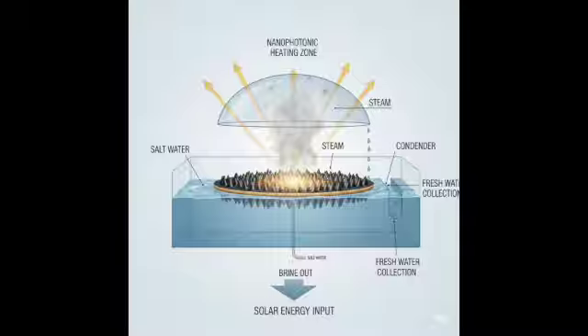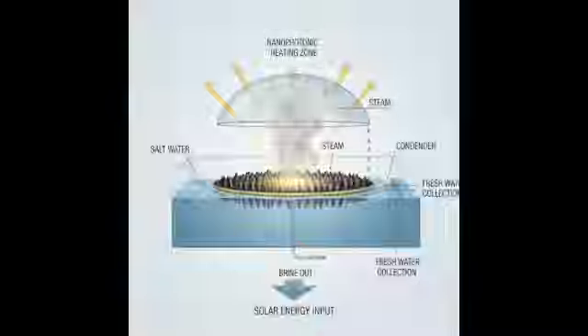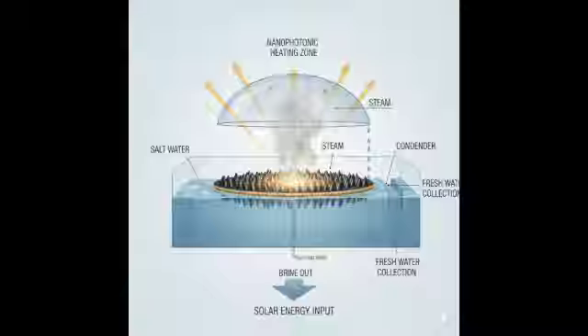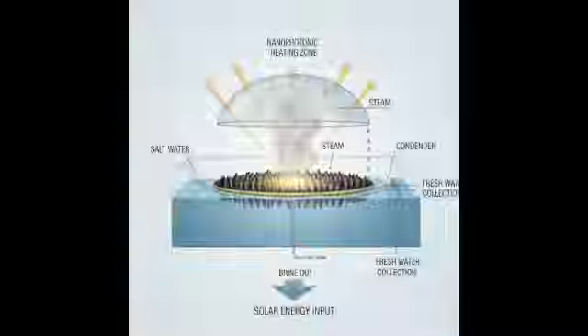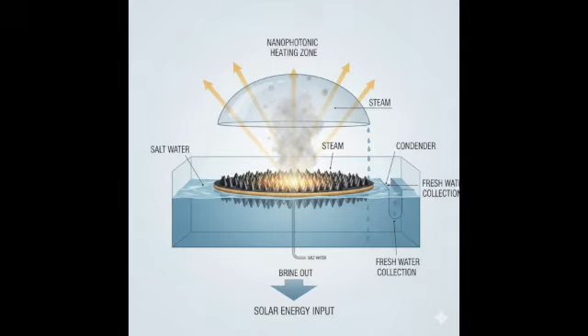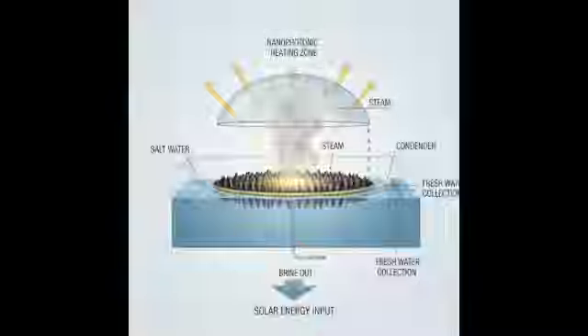You also mentioned earlier that unlike CMD, increasing module dimensions like the length of the channel might actually be good for PMD. Yes, that's an interesting potential advantage. In PMD, the feed water is continuously heated as it flows along the photothermally active surface. The temperature tends to rise along the channel length. So the driving force, delta T, might actually increase further down the module. It's possible, or at least be maintained more effectively than in CMD, where heat losses dominate over longer distances. This means that scaling up the module length in PMD could lead to a more proportional increase in total permeate production, whereas CMD performance often degrades with increased size. Okay, that's a significant point for scalability.